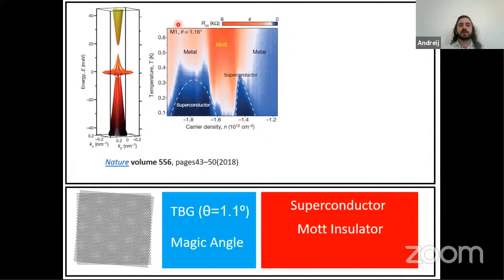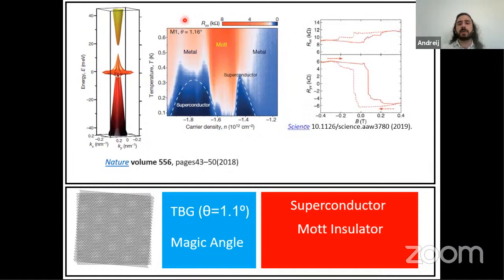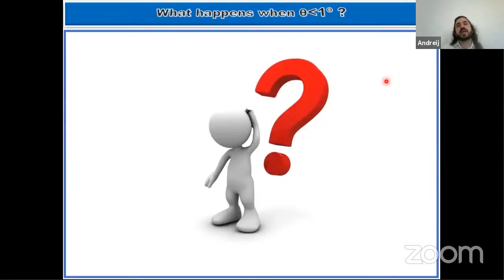And the TBG, as I said, behaves like a superconductor and a Mott insulator. On the other hand, this paper shows that in other electrostatic conditions, the magic angle twisted bilayer behaves as a ferromagnet. Okay, so this is a very interesting material. And what happens when we go down to lower angles? So angles smaller than 1 degree. A very nice material shows up with nice physics that I will show later.